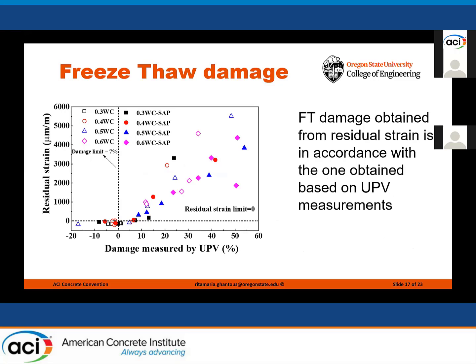Now, if we want to do a more direct measurement for freeze-thaw damage, we will be comparing the residual strain we measured based on length change measurements versus the damage index obtained from UPV to just be more confident with the results from TMA. So we can see that when the length change measurements show a damage residual strain higher than 0, the UPV measurements show also damage. And then when the UPV does not show damage, the residual strain has a value below 0 also, which indicates the absence of damage. We can then confirm based on this graph that the residual strain is a good indicator for freeze-thaw damage, and we will use this parameter, the residual strain, to look at the freeze-thaw damage for samples with SAP.